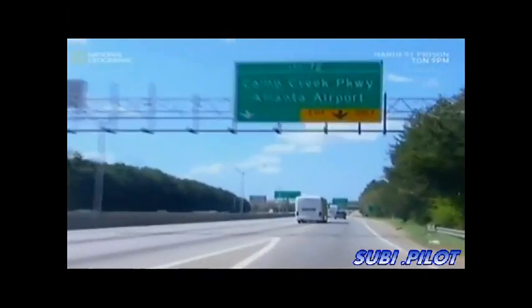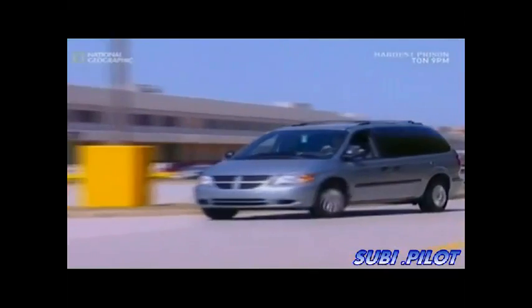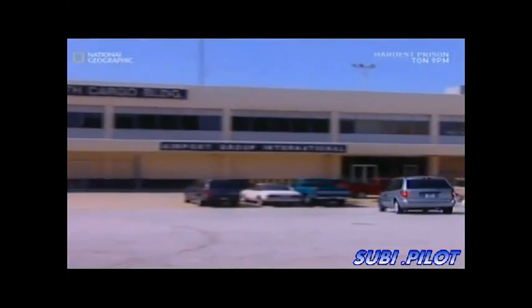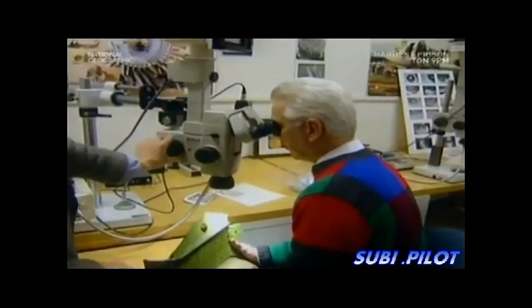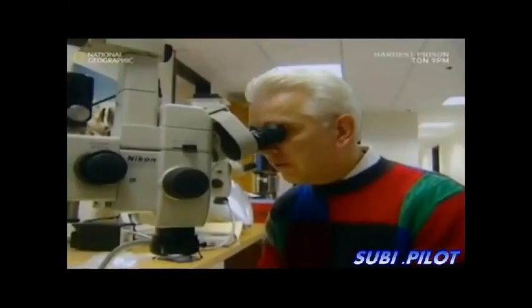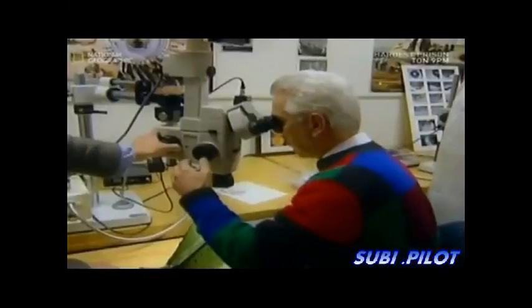Investigator Jim Hookey took the broken blade stub to Atlanta Airport. From there, it was sent to the NTSB laboratory in Washington. By next morning, blade number 861398 was being examined under a scanning microscope. Investigators found telltale deposits of chlorine, a corrosive substance known to eat into the inner walls of the propeller blade.